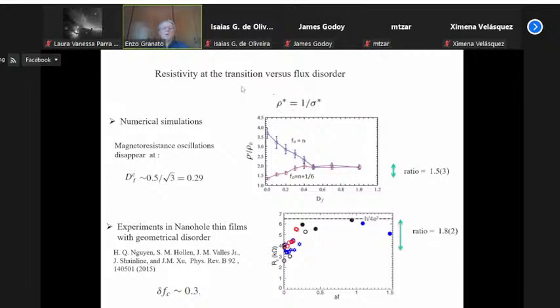And now here we compare with the experimental data. So the numerical simulation shows that the magnetic oscillation disappears at a particular value of disorder, which, when you convert it to the experimental system, is very close to what you see experimentally.